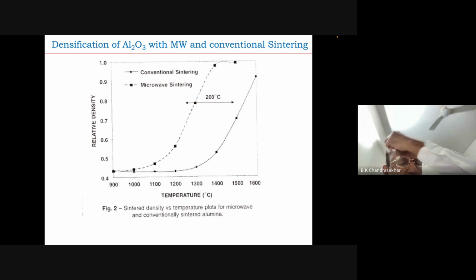And it will have some 0.25% of magnesium oxide, which is used as a grain growth inhibitor. You mix it with a little bit of water, typically 2-3%, a little bit of polyvinyl alcohol as a green binder, and also maybe CMC, some wax, things like that, and mix it very nicely. This powder you fill into a die cavity and press it.